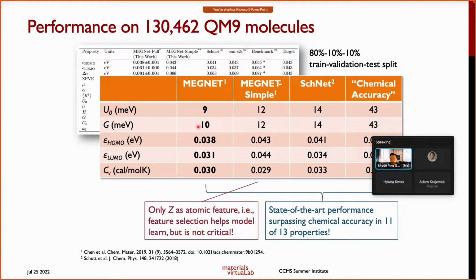We actually found that was completely unnecessary. Even if we use a simple model where we just use the atomic number as the atomic feature, we can get a model that has very comparable performance to the full MEGNet model, right? The reason is that the graph neural network is able to learn the mapping from, say, the atomic number to something like the chemical nature of that atom. All right.